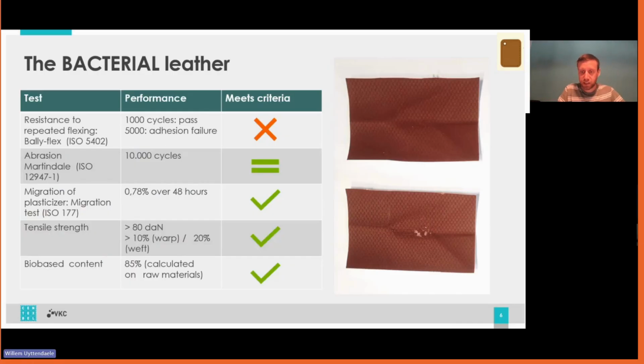If we do this with PHA, we get what you see here on the right, which is an artificial leather that really looks like a regular artificial leather made with, for example, a PVC. But this time around, made with PHA. Of course, we did a whole number of tests on these artificial leathers. And for most of the properties, we are really getting to what the market is needing for example, some handbags or things like that for artificial leather. So really abrasion resistance, migration of plasticizer, the strength is all good.